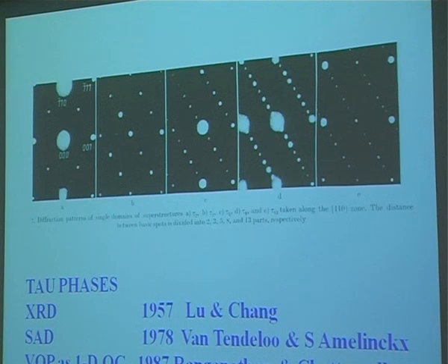And as Marjorie Senechal said this morning, quasicrystals want visualization. When you're able to see the patterns and the symmetry, then it triggers something in you. So in 1978, Van Tendeloo and Amelinckx produced these patterns. Tau 2, Tau 3, Tau 5, Tau 8, and Tau 13. In Tau 2, that basic reciprocal vector is divided into two parts. In Tau 3 into 3, into 5, 8, 13. They just reported like that, because at that time, the idea of quasicrystals, the idea of the Fibonacci numbers had not sunk in. So when we started work in 1984, 85, 87, we said these are the same as the one-dimensional quasicrystals.